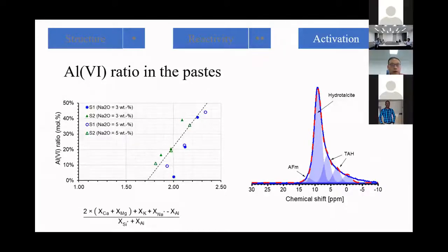We use solid-state nuclear magnetic resonance to determine the coordination state in alkali activated slag. From the results, we could also correlate it with our proposed non-bridging oxygen per tetrahedron parameter. From this plot, we could see clearly that this non-bridging oxygen per tetrahedron parameter can indicate the 6-coordinated alumina ratio in the paste.